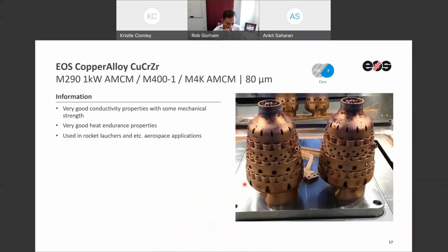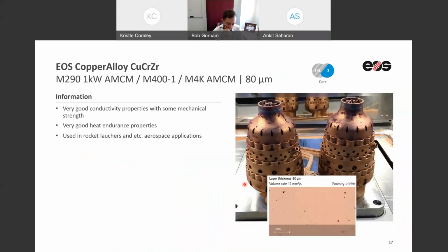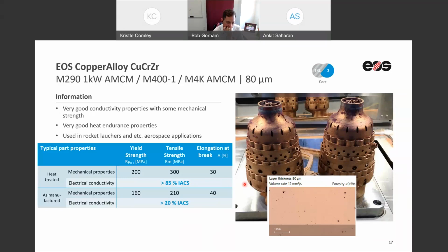Now, the last one, of course, is copper chromium zirconium. This is something that I said before, which is not only good in terms of conductivity, but also presents very high strength. It's also known as C18150 and closely resembles GRCop-42 in performance. The prime difference between GRCop-42 and this is basically the cost, where GRCop-42 could be about 3 or 4 times as expensive as copper chromium zirconium. But if we talk about the microstructure, it's almost 99.5% dense, with pretty high strength and, again, very comparable heat conductivity values, which, like I said, is very popular with the rocket industry.